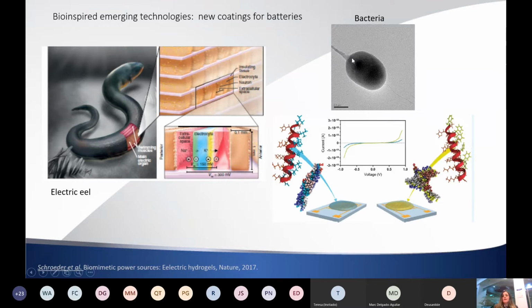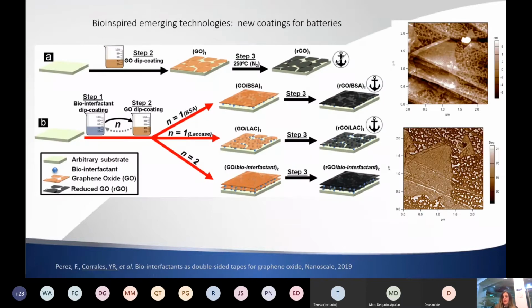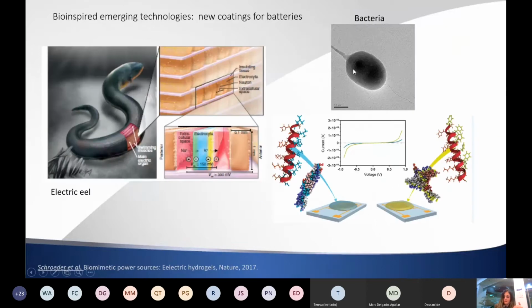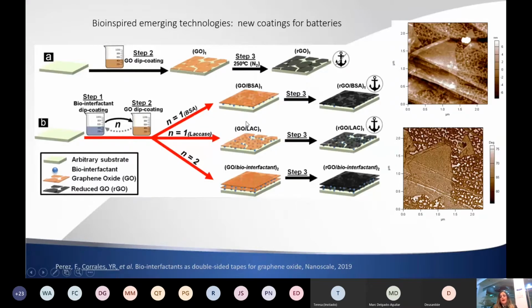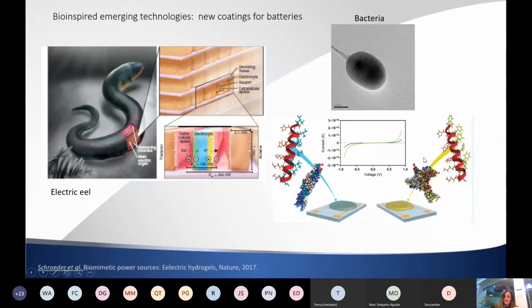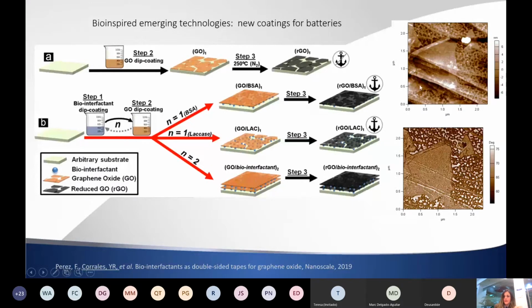For example, many people study the pili of bacteria because they can transport electrons fairly well to make these biomolecular junctions. And so we went further, and as we had these protein coatings with laccase that adhere really well to hydrophobic surfaces, we could build layers with graphene oxide. We developed a process, and we can really control it. Here is an AFM image. What you see here is graphene oxide, and here is the protein. This is the phase image where we see the contrast between the flat graphene and the protein.